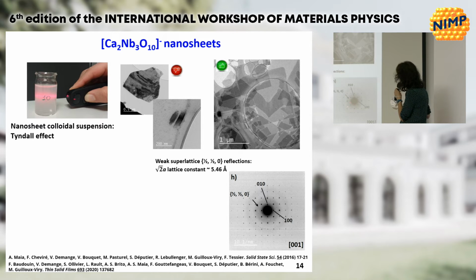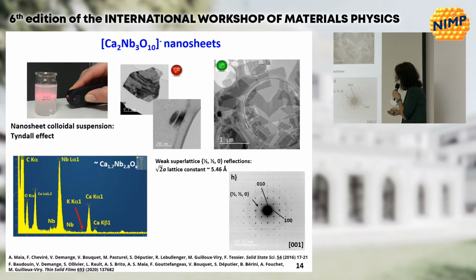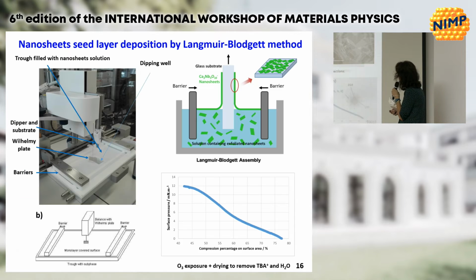So we see here we have the square pattern we expected for cubic materials, and we also see some weak superreflections corresponding to octahedral tilting in the perovskite layer. And again, we can check the composition, and here we have the disappearance of the potassium in the nanosheets.